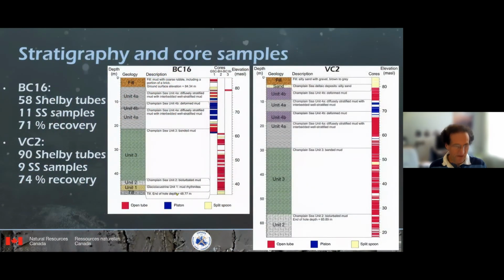In terms of the stratigraphy, we have the stratigraphy at BC16 and VC2 here, going from till at the base and then through units 1 through 4A and 4B. These were defined using the CT scans, as I'll talk about a little later. The recovery in BC16 is about 71% in 58 Shelby tubes and 11 split spoon samplers. We hit refusal at almost 49 meters. And then in VC2, we went a little deeper. We went to 66 meters, but we didn't reach till, which is at about a depth of 80 meters. In that case, we recovered about 74% in 90 Shelby tubes and 9 split spoon samples.